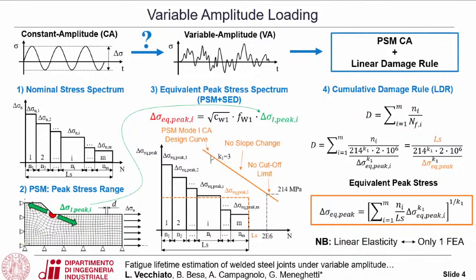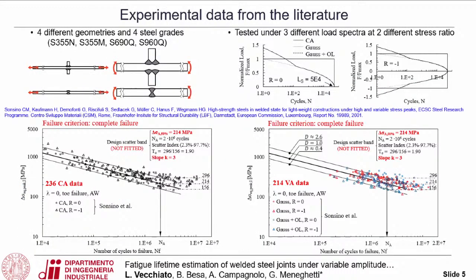Then the last step is just adopting the cumulative damage rule, the linear damage rule, and so it is possible to define an equivalent constant amplitude peak stress range. Just to check the validity of the proposed method, some data were taken from the literature, and in particular from the reported reference by Sonsino, Kaufmann, and many other authors that worked together in a European research program.